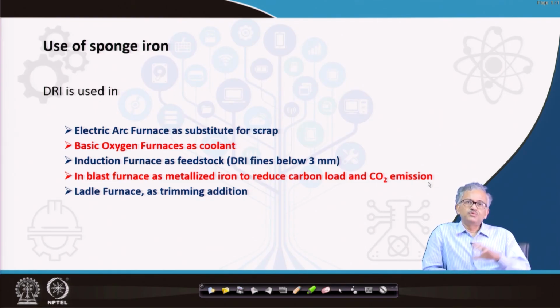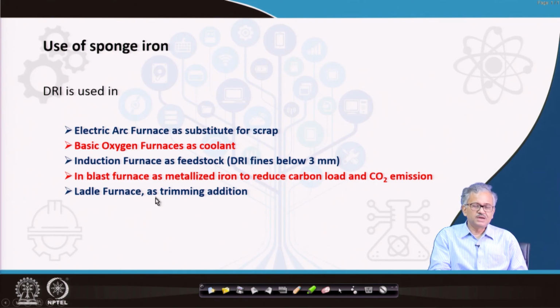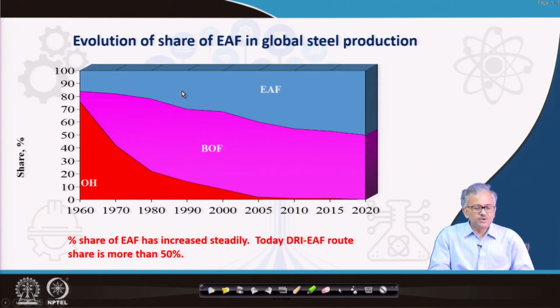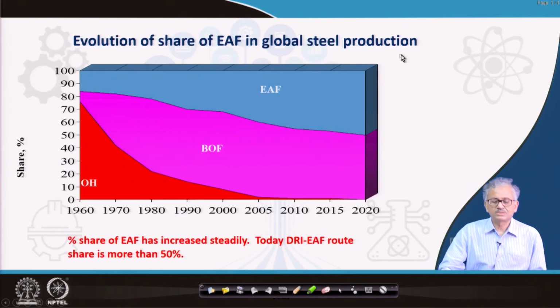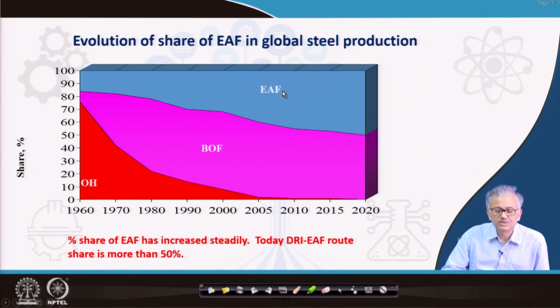Sometimes the DRI is not of very high quality, the metallization is not very high, and if you have used a lot of waste material, as a result final metallization is not high, that DRI you can directly put into the blast furnace, because in the blast furnace, since it is metallized iron, it will reduce the coke rate and it will reduce the overall CO2 emission. You can use it in the ladle furnace as a trimming addition, because you are alloying it, so you have to dilute it, so you can use the sponge iron there.